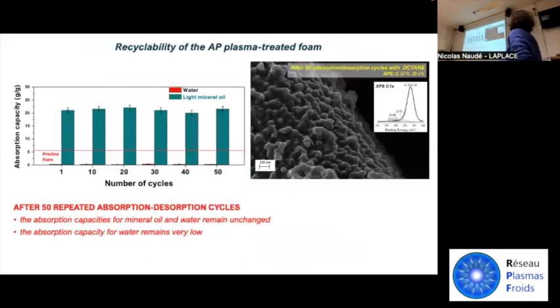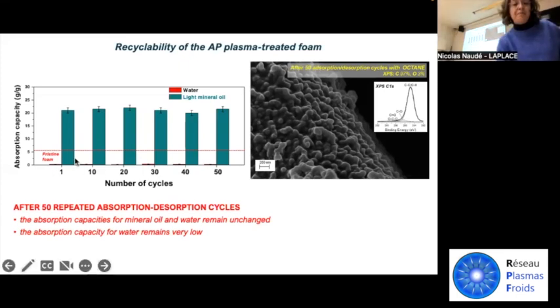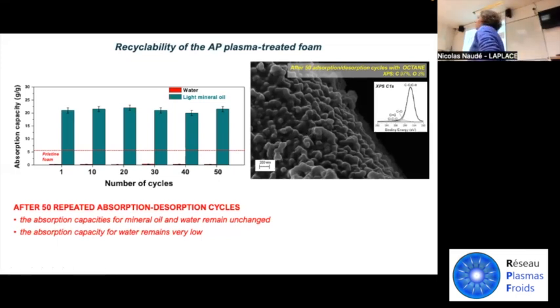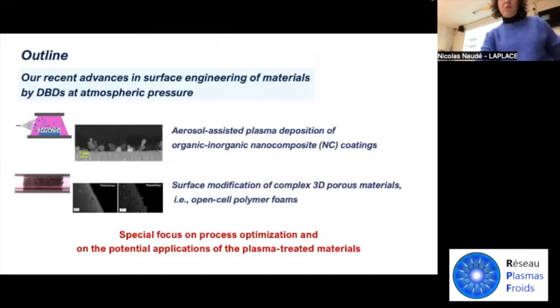And we explored, for instance, the recyclability of the atmospheric pressure plasma treated foam. And we observed that after 50 repeated absorption-desorption cycles, the absorption capacities for mineral oil and water remain unchanged. And most importantly, the absorption capacity for water remains very low, considerably lower than that of the pristine foam. And this is confirmed by XPS and SEM analysis. The surface composition is always dominated by the hydrocarbon polymer deposited from ethylene, and surface nanotexturing is always present even after 50 absorption-desorption cycles with water and a hydrocarbon solvent.